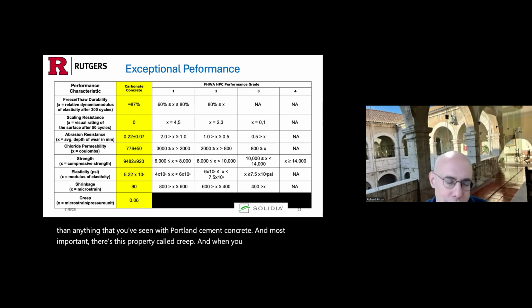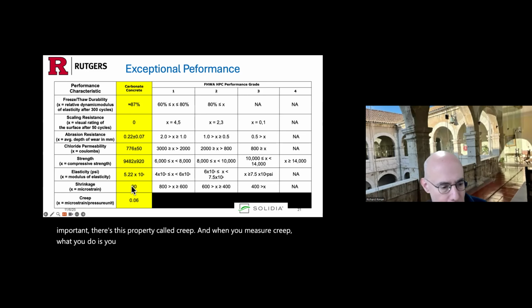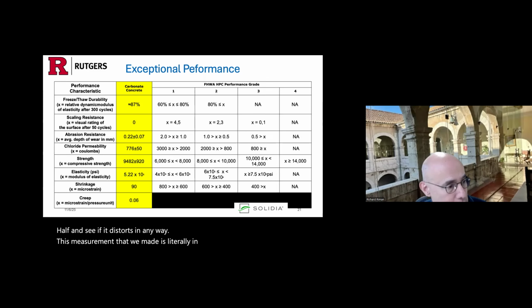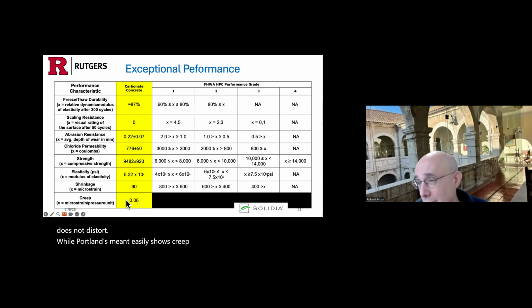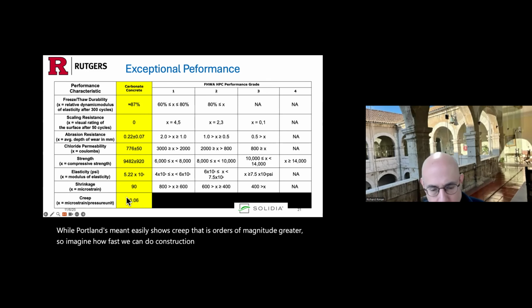And most important, there's this property called creep. And when you measure creep, what you do is you apply 1/3 of the fracturing stress on the concrete, and then you take it and you measure the material for a year and a half and see if it distorts in any way. And this measurement that we made is literally in microstrain. And it's literally in the noise or measurement uncertainty, meaning the material does not distort. While Portland cement easily shows creep that is orders of magnitude greater. So imagine how fast we can do construction if we started using material like this.